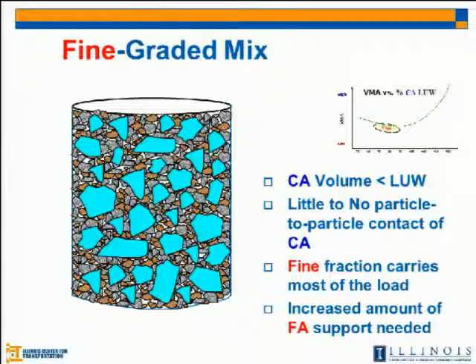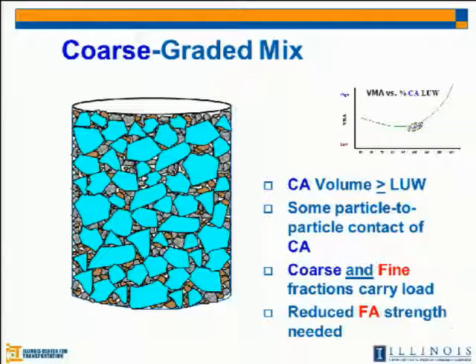The benefit of the fine dense graded mixture is, as people say, the compactability. If you use the fine dense graded mixture at a thinner layer, we can have the target density even at the thinner layer. For the 9.5 control mixture, when I talked with the plant people, they said they cannot compact this mixture at less than 1¼ inch thickness. But we had a good density, even at 1 inch or less than 1 inch, by using this fine dense graded mix.